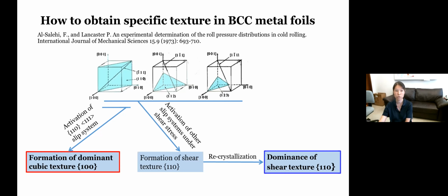So what you have to do is to apply a stress to the system. Then by activating the slip systems, right, if this one is the main one, you will be able to obtain a formation of dominant cubic texture of 100. So this is the {100}. Right now, of course, if the stress is too low, it's not working. And if it's too high, it's not working either, because by then you will be able to activate other slip systems, and this cubic texturing will no longer be dominant.